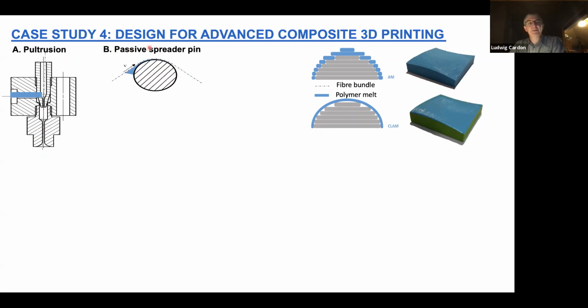A second method we developed is a passive spreader pin. A third method is what we call the active pin. What does this mean? The fiber will flow around this one, and the material will be pushed. So we spread out the fibers, but the material will be pushed in between the fibers. The method of the active pin is we have the filaments of the fiber flowing around the pin, and from internal, we inject the polymer, the matrix material, inside the fiber filaments. So to improve the infiltration.